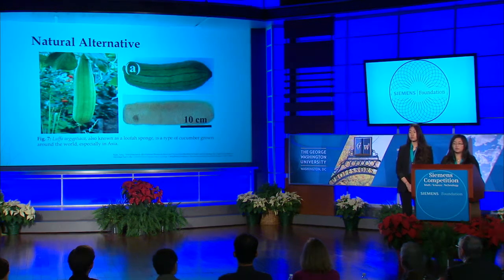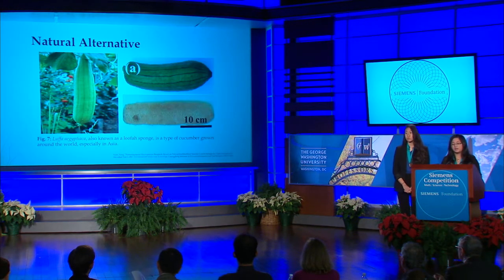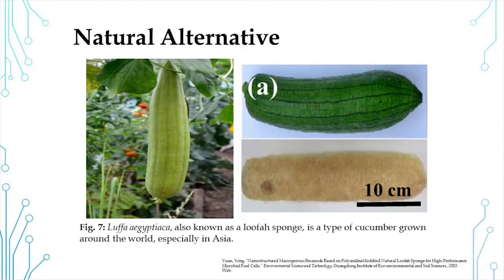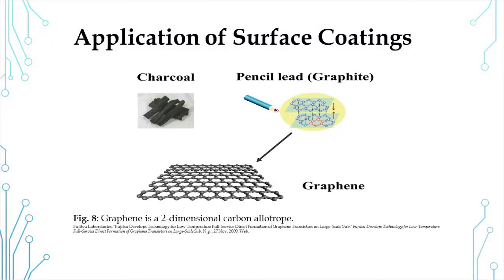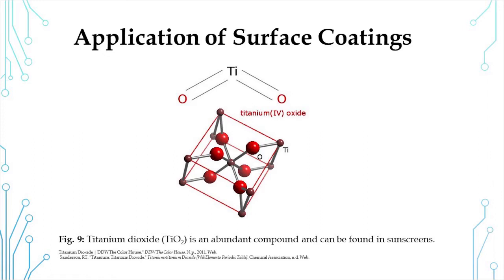The use of a natural organic material can act as a cheaper alternative, in which a loofah sponge has a similar structure to RVC, and the carbonization of this material can create an electrically conductive carbon alternative. In an MFC, an electroactive surface coating can enhance the anode properties. Graphene is a two-dimensional carbon allotrope that has high electrical conductivity and high specific surface area. Titanium dioxide is a popular semiconductor that has low cost, high abundance, and high chemical stability.